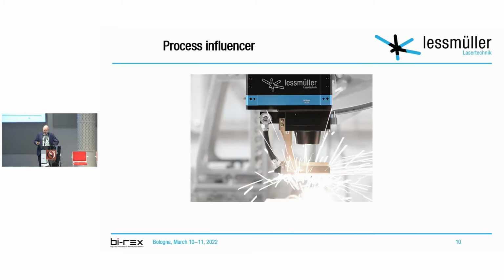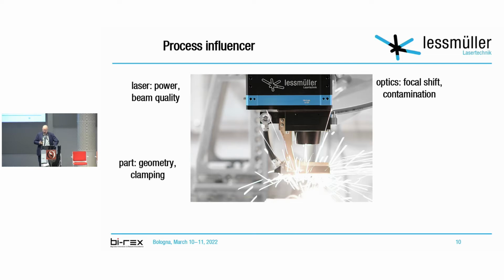And the laser itself is a very stable process, as we know, but you still have influencers. The laser power can vary, the beam quality can vary. Our optics are not perfect. You have focus shift, you have contamination of the optics, you have the part itself that may vary in geometry, the clamping. Clamping is an always underestimated influencer. You have the materials, the alloys that may change. You have the surface, depending on your pre-processes, that varies. You have pollution during the pre-processes. And your motion system may vary in speed, may vary in positioning.